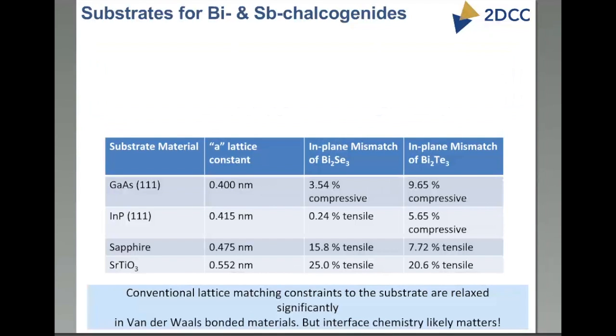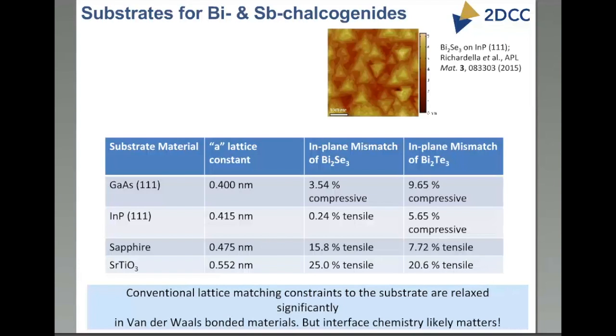Now, with these van der Waals bonded systems, so all of these layered materials, chalcogenides, they are unlike gallium arsenide or zinc selenide or silicon. There is van der Waals bonding between units of the lattice structure, and it turns out that really relaxes these constraints of lattice matching, but not always, and sometimes in surprising ways. So, for example, let me show you an AFM scan of bismuth selenide grown on indium phosphide. If you look at the table here, you'll see that the lattice mismatch in plane is quite small. It's only 0.24%. Nonetheless, when you grow these materials by MBE on indium phosphide, you start getting these triangular or mesa-like structures on the surface.